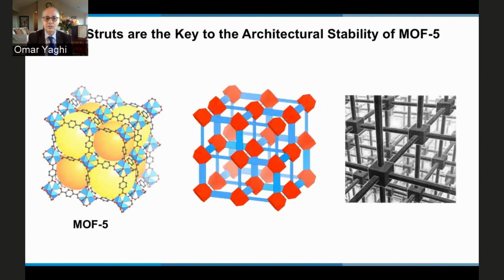So MOF5 is very special in its architectural robustness. And that's because if you look at the crystal structure of MOF5, and look closely, you find that the terephthalates are actually at 90 degrees to each other. This is 90 degrees to this one, in that they turn 90 degrees with respect to each other. And they also, of course, have these 90 degrees. And that's the best way to build a structure, even if you were trying to build a building. These are the sort of interactions that you want to maximize to build a robust architecture. And that's exactly what we have in MOF5.